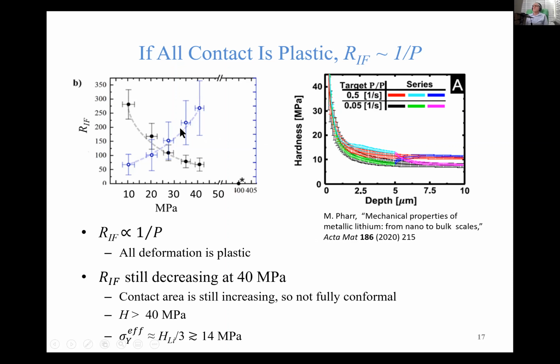What this means is that this data here, where the interfacial resistance is still falling at 40, and Pharr's data, are perfectly consistent as long as, to the lithium, the solid electrolyte looks like a bunch of submicron indenters, and that's not hard to believe. Because the yield strength varies so much with the size of the indentation, and we expect all different sizes in a realistic solid electrolyte, we're going to treat the effective yield strength as an adjustable parameter in this model.